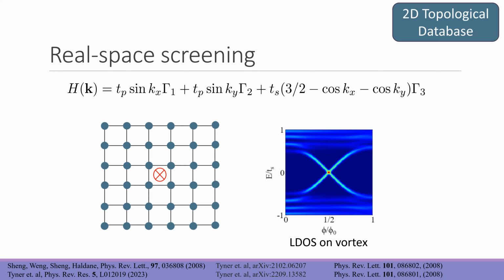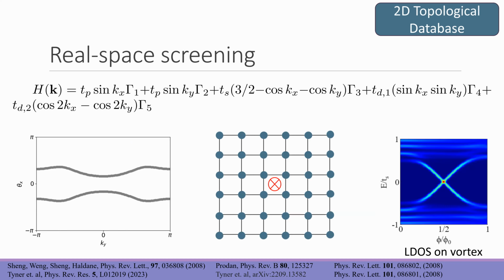Here on the right, you're looking at the local density of states on this flux tube as a function of the flux strength. You can see that this has spin Chern number 1, and it's binding a single Kramers pair. And we can see that this Kramers pair is pumped across the bulk gap as a function of the flux strength in this case. So this is a real-space probe, an alternative way of probing topology, and I'm going to show why this is important or useful.